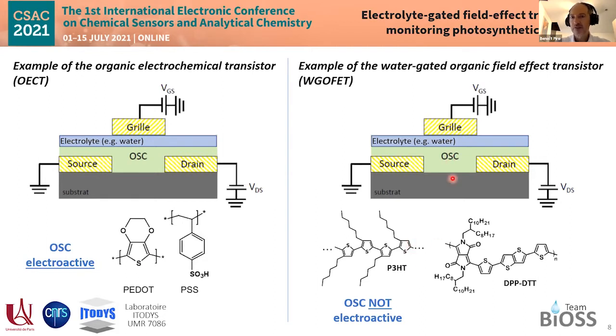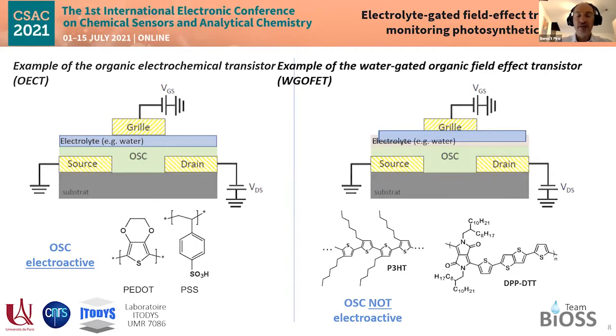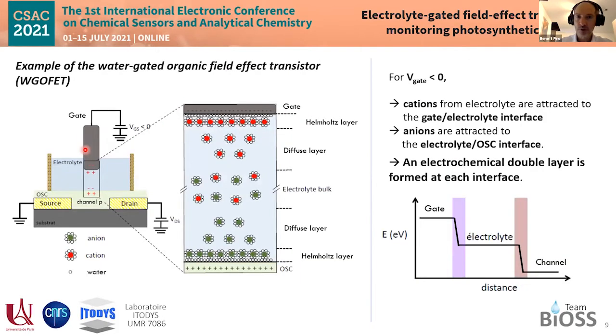It is not, even if in direct contact with the electrolyte, and is selected to behave as a true organic semiconductor, typically P3HT, DPP-DTT, or many others, which are stable in contact with water and stable with time, stable in contact with oxygen as well, and not electroactive again. So if they are not electroactive, that is, if there are no ions going through the semiconductor, upon application of a gate voltage